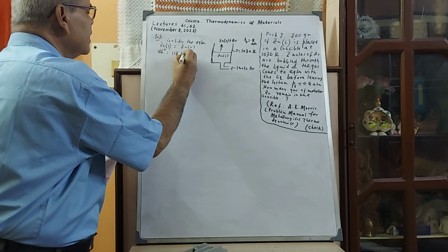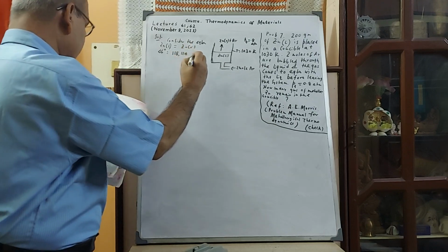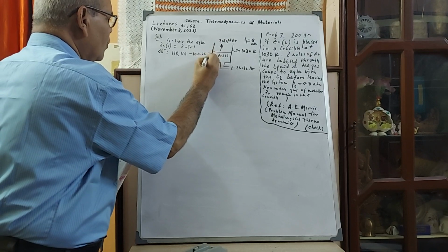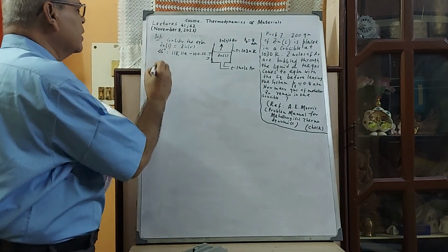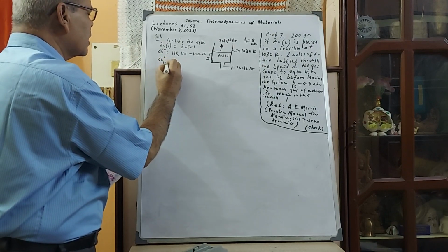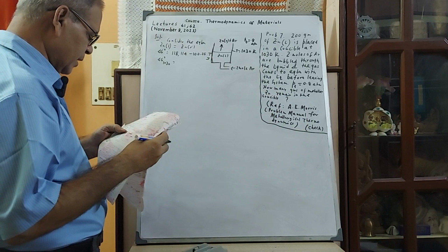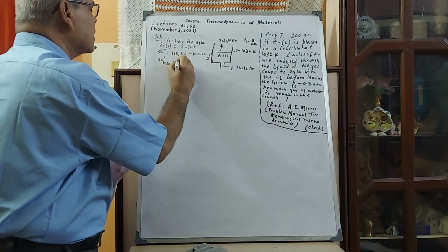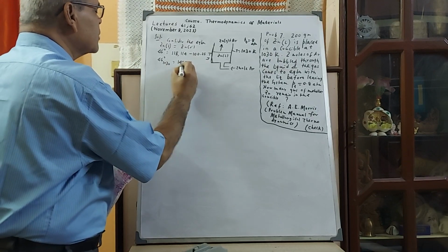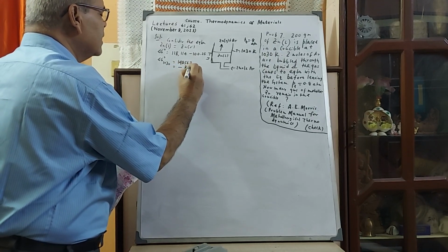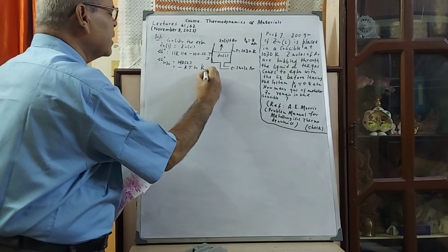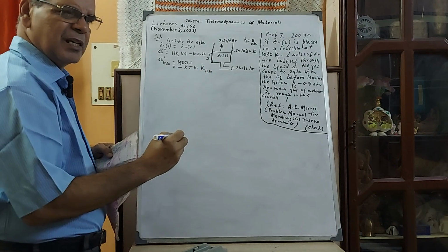Delta G0 is 118,114 minus 100.25 T joule. This is as it should be. Then what will you get? Delta G0 at 1030, you tell me. That is a routine job. You get 14856 joule. And you substitute here: minus RT ln K, with K at the same temperature. You should always tag the temperature with delta G0.